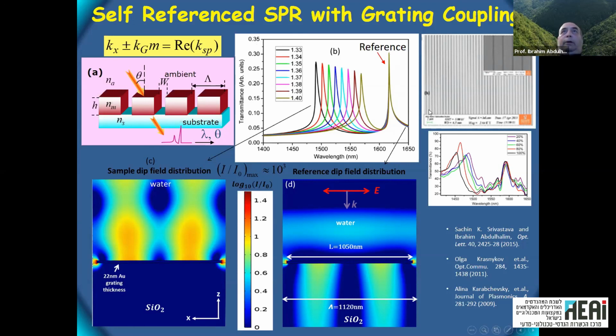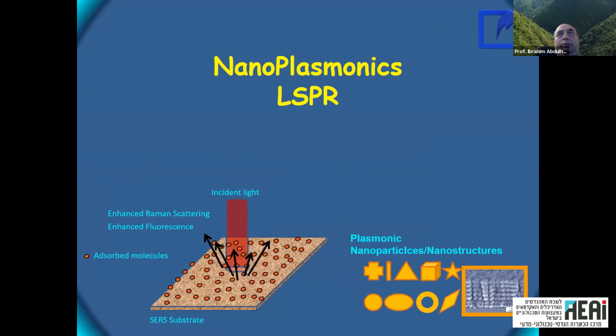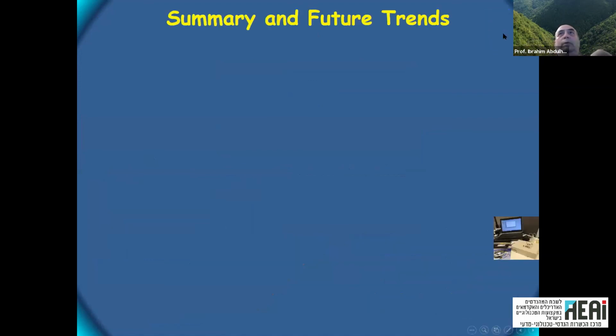But here we found that if we use the grating to be very thin, first of all, you improve the transmittance and also you get self-reference. And this is the proof of it. And you can enhance also the field quite largely. So you can use it for enhanced spectroscopy. So I will not have time, unfortunately, to talk more about nanoplasmonics. So I will jump to the summary.